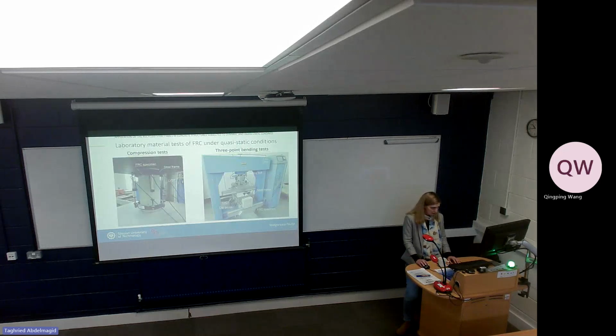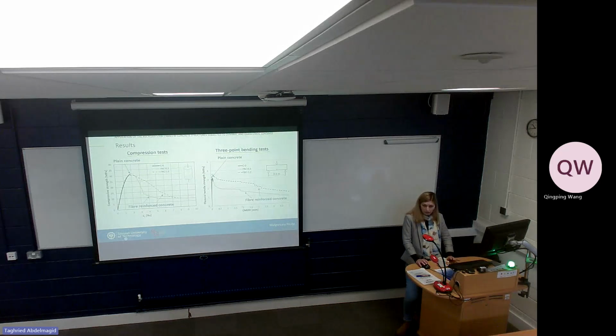So what are the tests that we usually do? That is recommended, of course. So the compression test must be done, and the 3-point bending tests that I have already discussed. And what result do we achieve when we test the concrete and the fiber reinforced concrete? So for the concrete, when you start to compress it, you will get the maximum value. And here, of course, there could be like this. It just splits out after the tests.